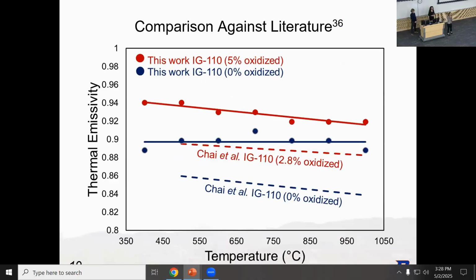For IG-110, we compared our results versus a paper by Chai et al. from 2020, which had a very similar experimental setup. Our work is shown by the solid line and the Chai paper is by the dotted line. And what we saw is that our emissivity was measured about 0.04 higher than that study. This represents about a 5% error in comparison to theirs.